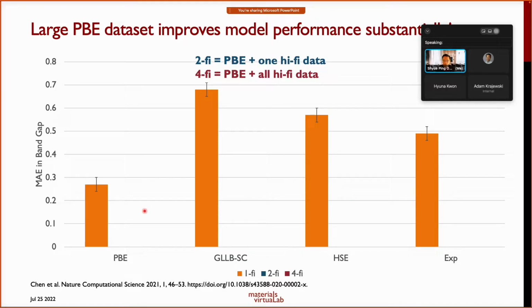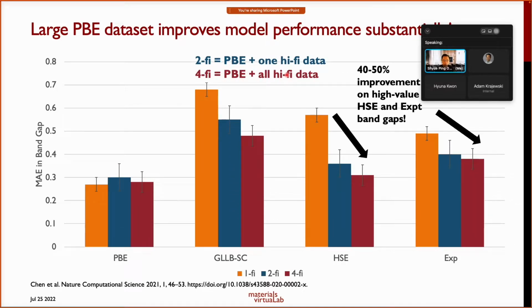So what happens when we use our multi-fidelity graph network and we combine the largest data set, which is the PBE data, with at least one of the high fidelity data sets, or we combine all the fidelity data sets together, right? And this is basically what happens, right? The blue is basically what we call the 2-fidelity models, and the red is what is called the 4-fidelity models. And what you immediately notice is that we get a 40 to 50% improvement in our prediction of the HSE and experimental band gaps, right?